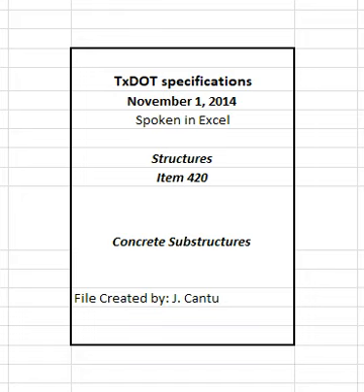4.7.14 Mass placements. Develop and obtain approval for a heat control plan for monolithic placements designated on the plans as mass concrete to ensure the following during the heat dissipation period. The temperature differential between the central core of the placement and the exposed concrete surface does not exceed 35 degrees Fahrenheit and the temperature at the central core of the placement does not exceed 160 degrees Fahrenheit.